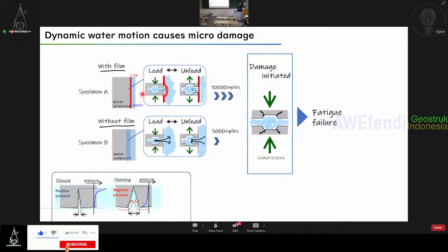With the latex film, water cannot go out, and of course water cannot go in. So water motion is very limited at the surface. But with no latex film, water can easily go out and easily go in. So microstructural failure can be promoted. Afterwards, in the case of film, 10,000 cycles, and with no film, 3,000 cycles, and then fatigue failure. That is the key mechanism of fatigue failure as I understand it.